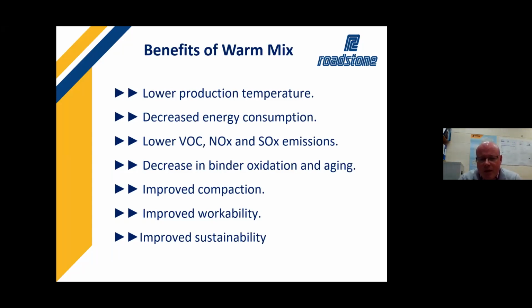The big benefit that a lot of the additive companies are saying is that because you've reduced the mixing temperatures, you've actually changed the environment within which you've made the materials, so that the bitumens will age less as they're being produced, or as they're being made into asphalt materials and bituminous materials, because of those increased temperatures. So that aging and oxidation of the material doesn't get to happen because you don't have that higher temperature that has been noted before. Because of that, they believe that the materials will potentially have a longer life because they haven't had that initial phase of aging, and that they will outperform standard materials in the long run.